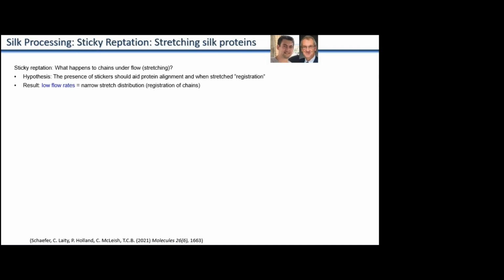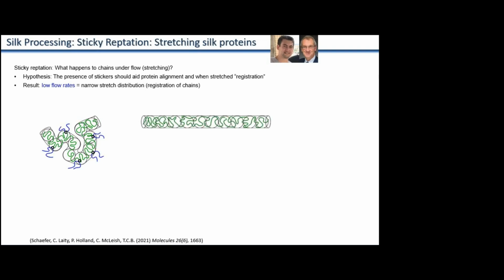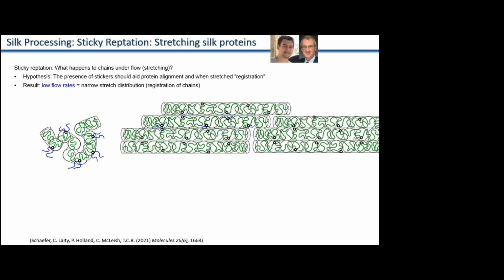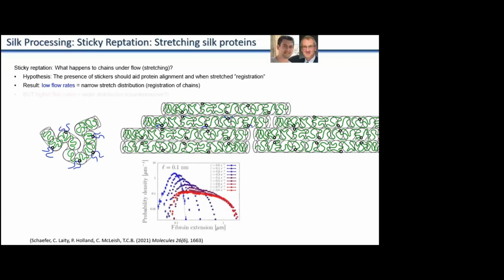At low flow rates, they're stretched out, and the stickers that are still present will allow them to interact with the other chains. So you can almost imagine them a bit like magnets, where they're just sort of aligning those chains to one another. And then when you really ramp up the stress and pull them and remove that water from around them, they'll snap together. So we think that this stickiness is the registration of the material.